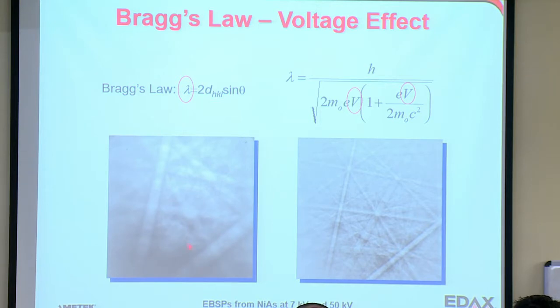So at high kV, we get very sharp lines, and they're much narrower, and you can see many more reflections in the material. So we typically operate around 20 kV, but in a typical SEM arrangement, you can operate down to, say, 10 kV. There are a few microscopes, SEMs, that can go to higher voltages, such as 30 and up to 40, and I guess up to 50. This is a pattern given to me by a colleague. I'm not really sure where it came from, but typically you can't get to 50 kV in a typical SEM.